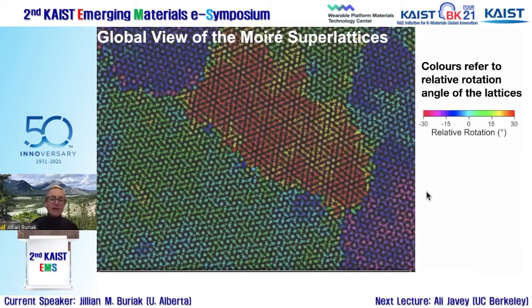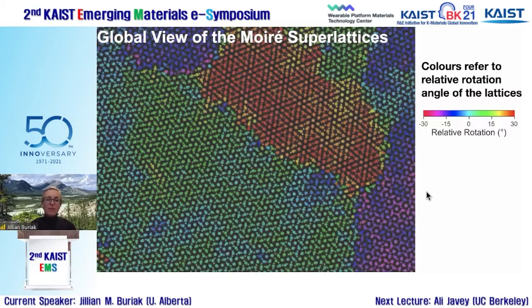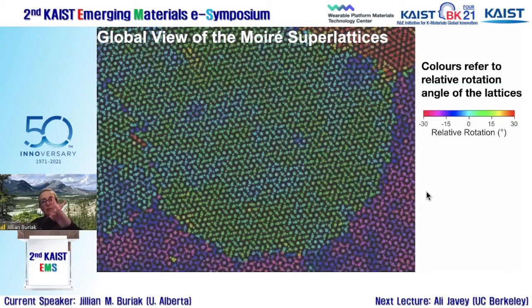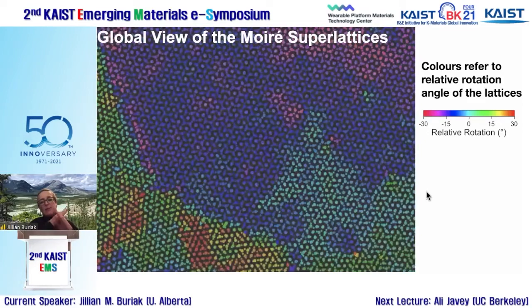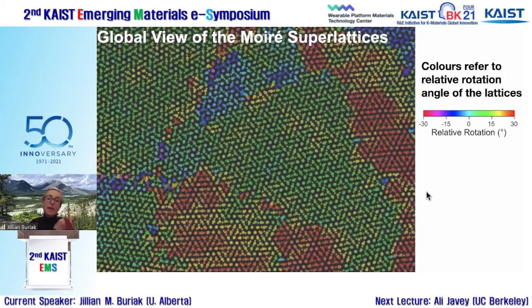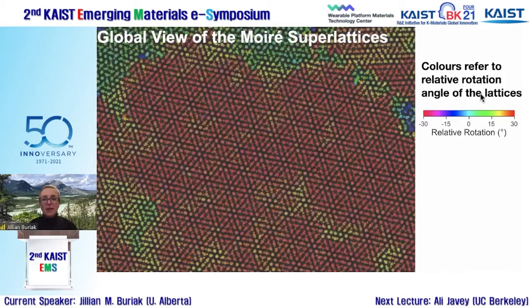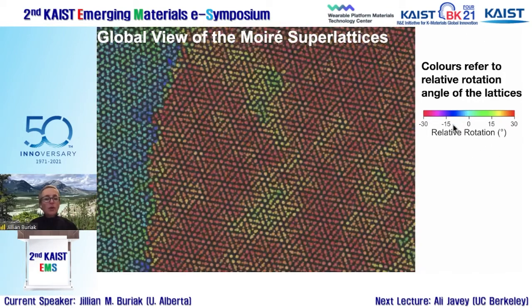And what Brian did is that he then wrote an algorithm that would actually color code this by the angle of rotation. And so what you see is that red is plus or minus 30 degrees. So these are in fact chiral phases. And then in the middle, you can see that he adopts the more neutral blue and green.